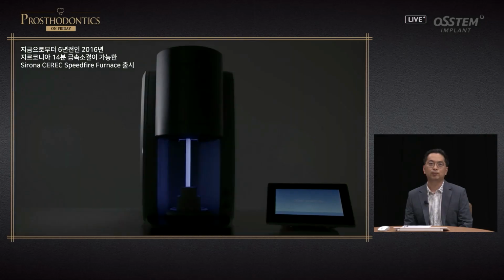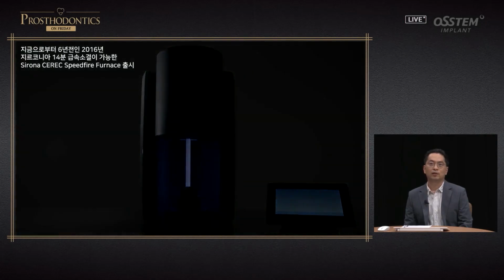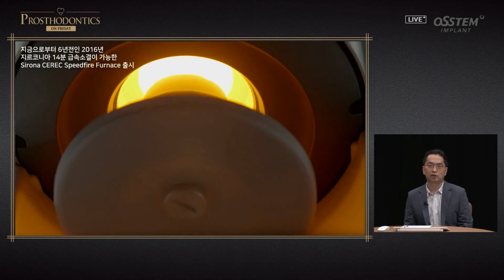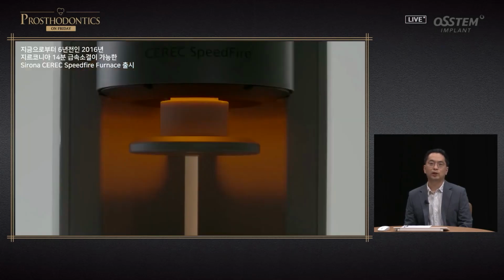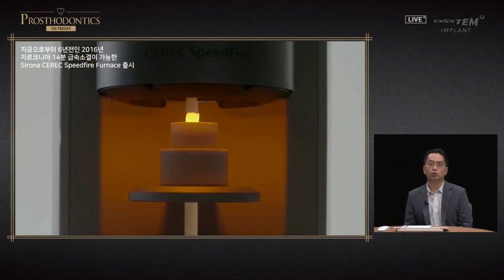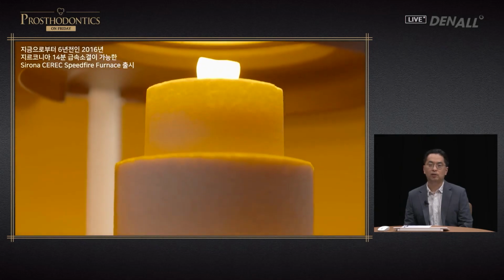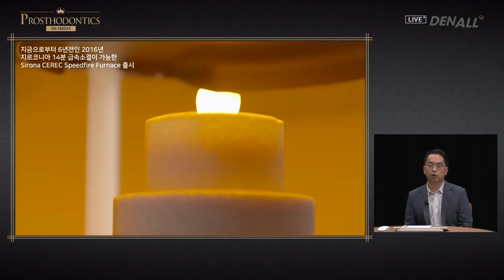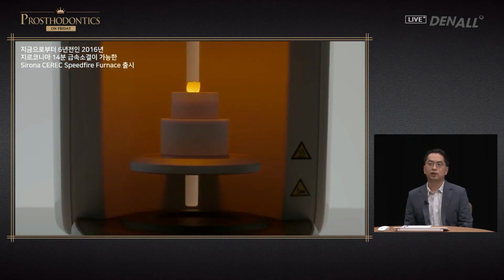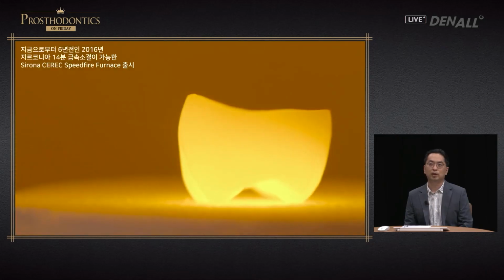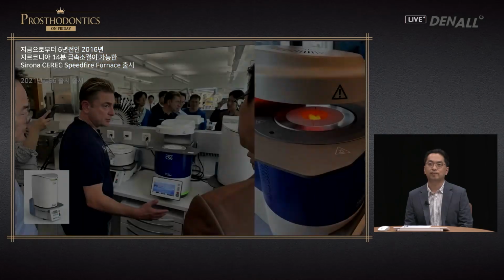About 6 years ago, in 2016, Dentsply Sirona released the Cerec Speed Fire furnace, where rapid sintering within 14 minutes was possible. Since 6 years ago, one-day zirconia sintering has been possible. It was used clinically. This is a closed system, and the Cerec system was required.